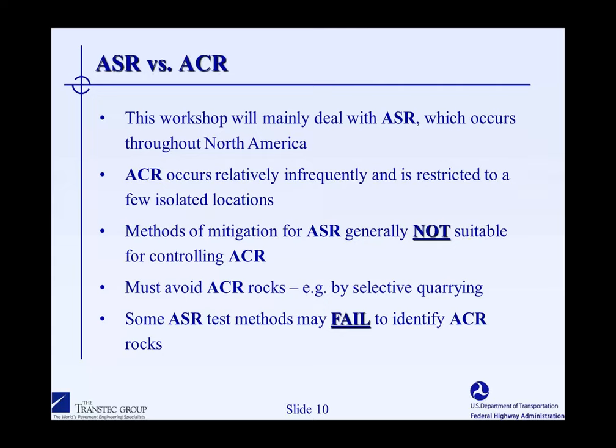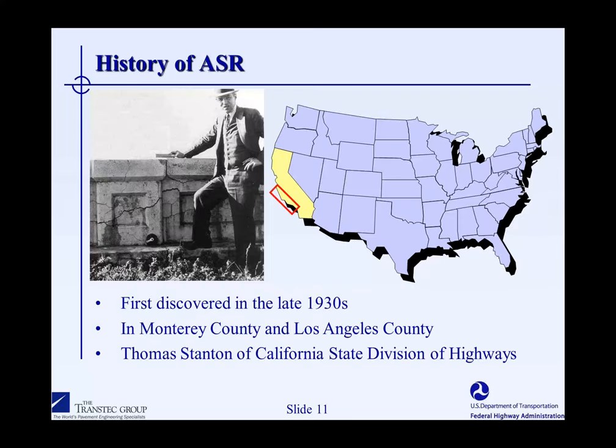One of the important things to distinguish between ASR and ACR is if we have alkali-silica reactive rocks, there are things that we can do to enable us to use them safely. ACR, on the other hand, alkali-carbonate reaction, cannot really be prevented, and the only way to deal with this is by avoiding the reactive phases by selective quarrying. And another thing to bear in mind, which we'll get to later on today, is that some ASR methods may fail to identify alkali carbonate reactive rocks.